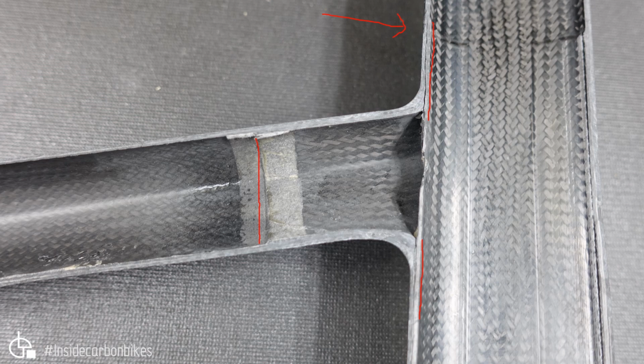So as I said before, you've got the interlaminar shear strength of the resin holding those plies together. Now, typically, but not always, and there's a lot of work being done in this area, injection resins often have lower mechanical properties than a prepreg, high temperature curing resin. So it's a bit of a generalization. I don't like making generalizations like that, but often the cure temperatures aren't as high, so you don't get as much cross linking. It's also more difficult to add additives to an injection resin, because often they can almost be filtered out during the injection process.